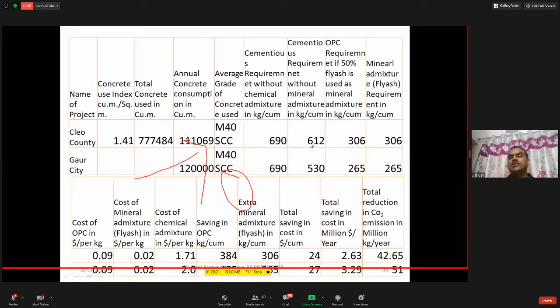When we use the chemical admixtures, it has reduced to 612 kg. And when we use 50% fly ash, it is 306 kg and 306 kg. And if you see, the cost of the cement, mineral admixtures, and everything is added here. So total saving in OPC cement is 384 kg per cubic meter of the concrete. Extra mineral I am adding is 306 kg. If I add the cost of everything, I am getting a total saving of 24 USD per cubic meter of the concrete, and total saving in a year is $2.63 million per year. Carbon dioxide emission saving is 42.65 million kg of carbon dioxide gas reduced per year.